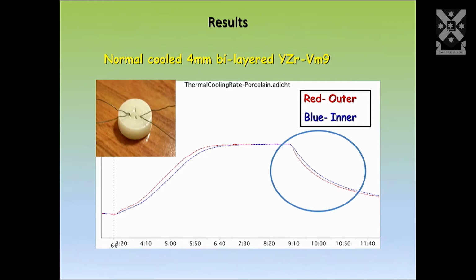And to validate that, we took tablets of porcelain and we put thermocouples, one in the center and one on the outside, and we heated it up until the two were at the same temperature, and this was above the glass transition of the porcelain. And then we cooled them at different rates.